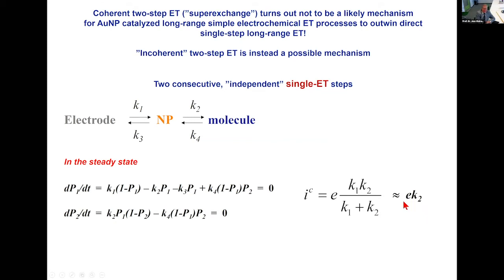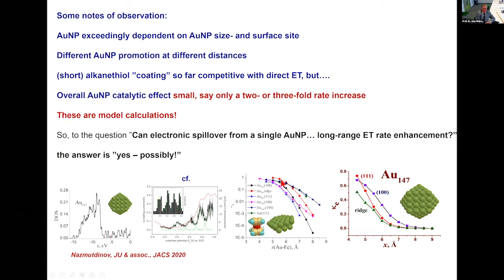So ultimately, what we compare is the rate constants for electron transfer between the nanoparticle and the molecule, or between the electrode and the molecule. And that is summarized here. We calculate the electronic structure. Here is the density of states, and you can see it resembles to some extent what we've seen experimentally. And then we can calculate the electronic transmission coefficients and the rate constants and see what comes out of it. And we can see one thing: the catalytic effect, if you call it that, is exceedingly sensitive to the actual surface site of the particle. The particle would have peaks and vertices and facets, and they have widely different effects on the transmission coefficients.